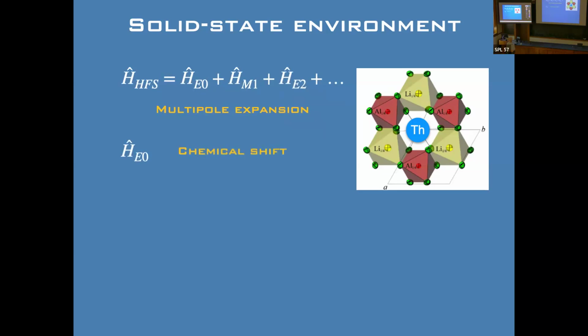There's a term you might call the chemical shift. It's just an interaction of the nucleus with the electronic wave functions nearby, and you can think of it as a contact interaction, if you will. It's well known in NMR or Mossbauer spectroscopy. If you run the numbers, this gives you a shift of a few megahertz relative to the free ion, but it's just a shift if the thorium always goes into the same lattice site. It's a common mode shift. You can also get a temperature-dependent shift, because as you change the temperature, the crystal contracts, and so this changes a little bit. That's generically kilohertz per Kelvin.